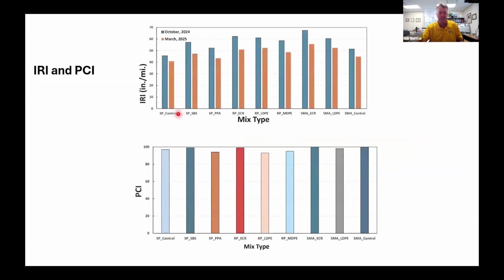And then as far as international roughness index, with asphalt you can hit 40s and 50s after construction. Sorry, concrete industry, you can't do it. We can. And those have stayed pretty good. Because of the seasonal adjustment and roughness with the concrete pavement, we actually saw a little bit of decrease in IRI the second time we went out, but statistically similar and low. And then the PCIs are all still between 90, 95, and 100. So really, reflective cracking is the only distress except for that small section of bleeding.